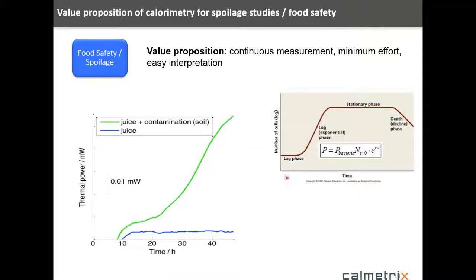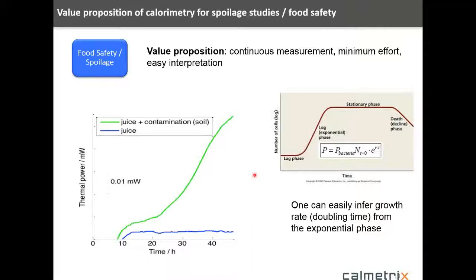And if you compare that to what you might classically see in your data, it looks very similar, especially when you start thinking about the log, the exponential phase of the curve where things are growing. These curves are shaped very similar. It's just that rather than looking on the y-axis at the number of cells and the doubling of cells, we're looking at thermal power and the fact that a doubling of thermal power relates to the doubling of the number of cells. And the point is that you can use all the same equations that you use right now for studying your curves. And you can infer the doubling times by looking at these exponential portions of the curve and use all the same equations that you're used to using.